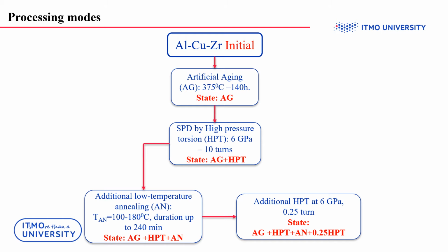Artificial aging at these parameters was carried out for homogenization and formation of precipitation of the nano-sized metastable phase of Al3Zr. The UFG structure was formed by high pressure torsion at room temperature. A part of the HPT processed specimens was annealed at various annealing parameters in order to study the effect of annealing on the physical and mechanical properties of the UFG alloy. Finally, after annealing, the effect of a small additional HPT deformation on the strength properties of the alloy was studied.